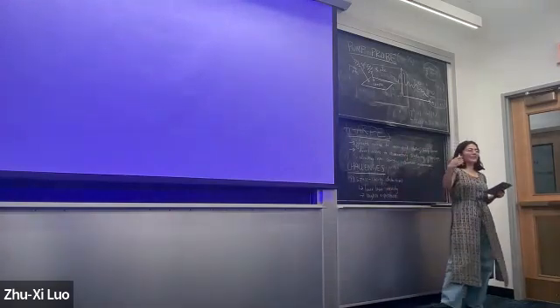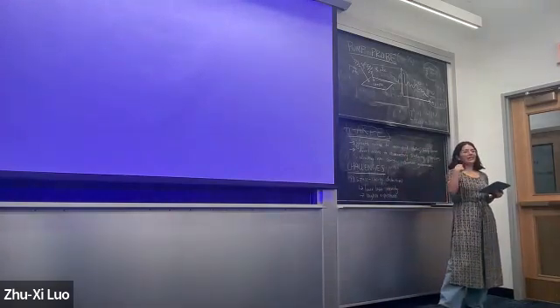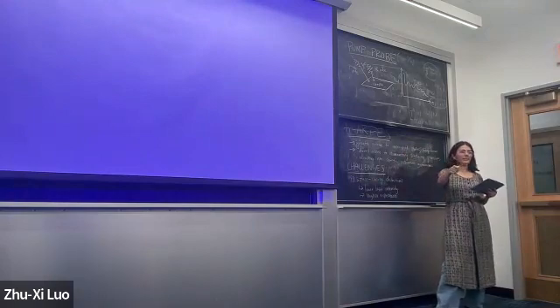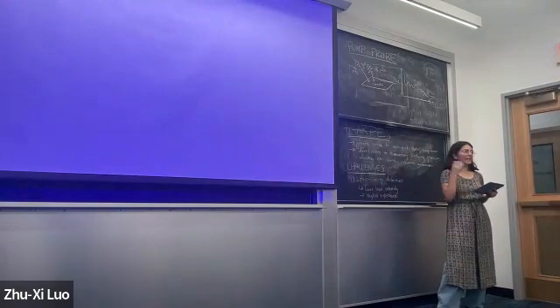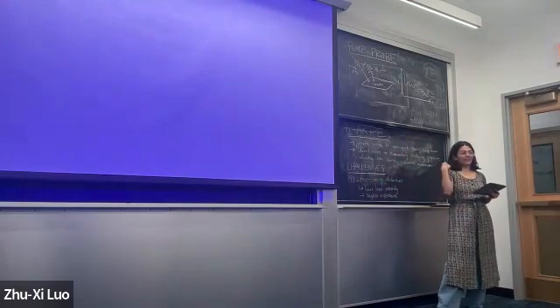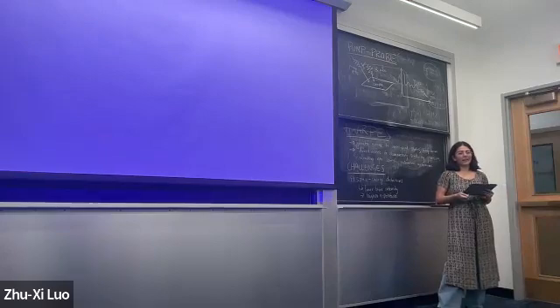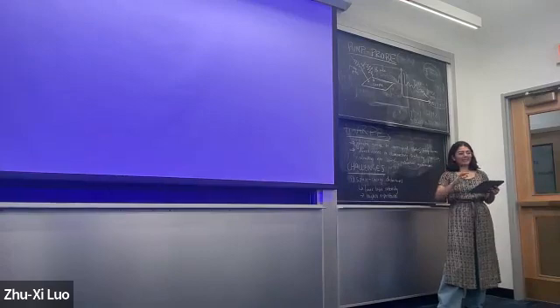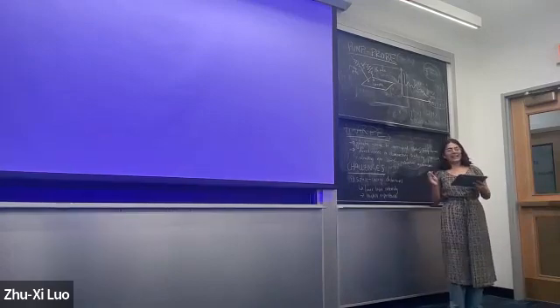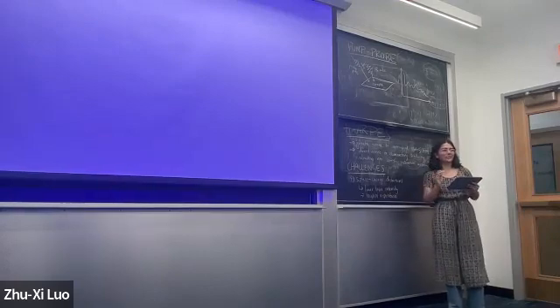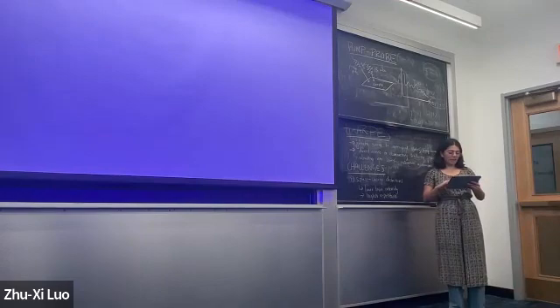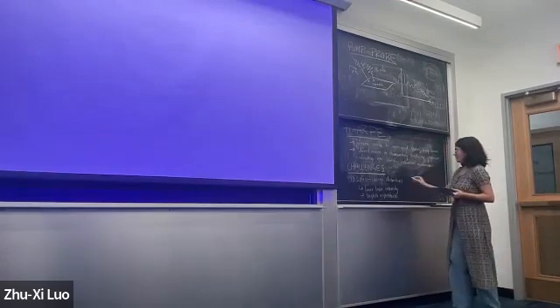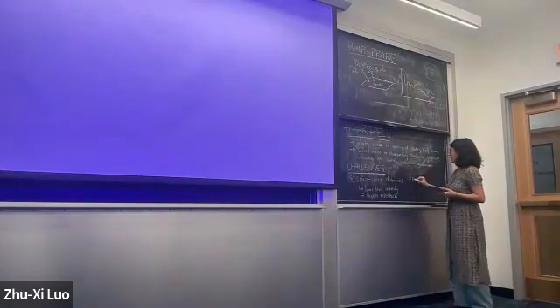And this comes along with its own issues, because if you have a very high rate of repetition, you're sending in these pump pulses very quickly. Your system might not have time to equilibrate in between when you excite it. And so you'll get heating of your sample very quickly. And this also doesn't lead to good data. So you also have to optimize the repetition rate of your laser. In any case, I get the sense that repetition rate is not something that's necessarily easily tunable in these laser systems. And then, yeah, you also want to minimize heating.